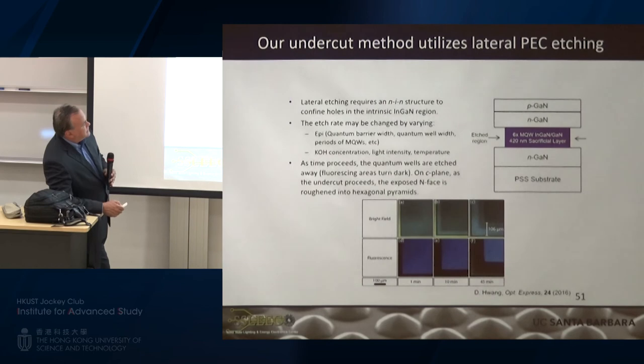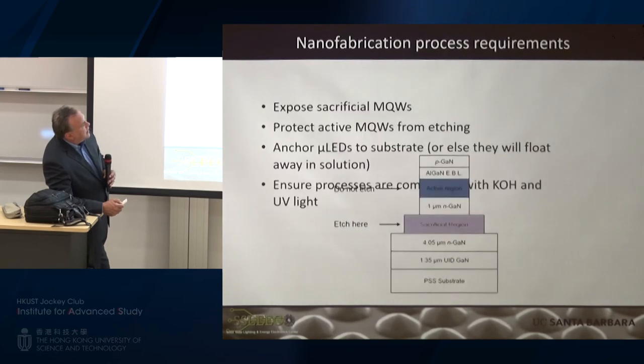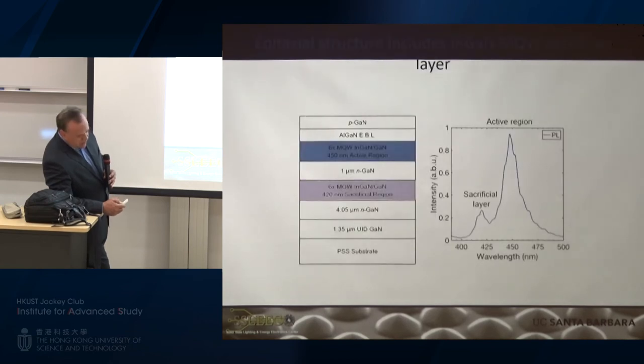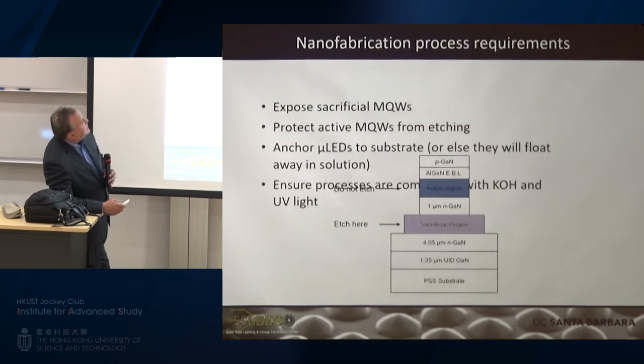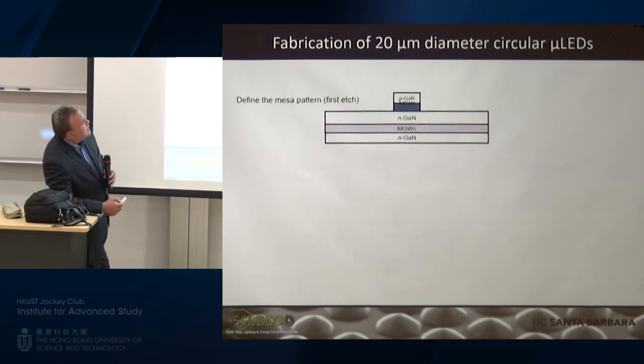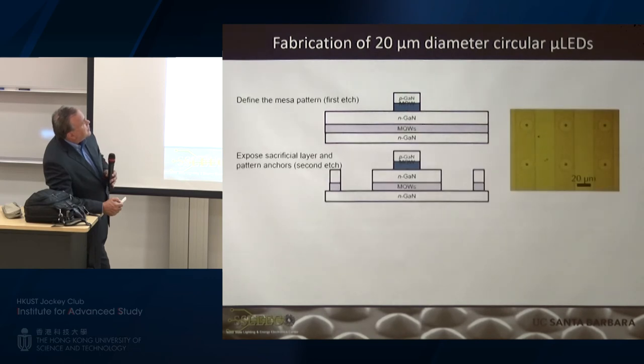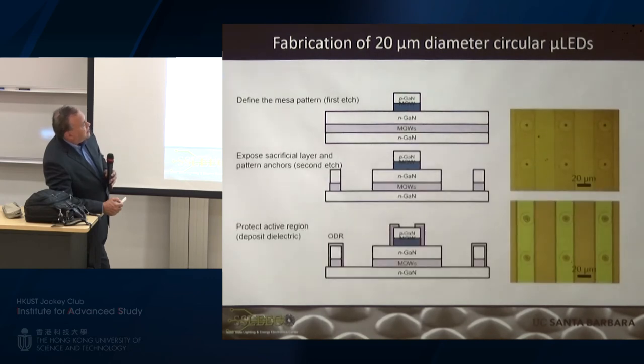Just show you this. So this just shows you as time progresses. So in 45 minutes, this is one of the micro LEDs you could see. We could just come in from the side here and etch away the sacrificial layer here. And it shows you as we etch it away. Oops, this didn't quite show up. We're able to then go from a substrate like this to then single freestanding little micropixels, basically with the following process. So we then pattern them and look at them on a scope.